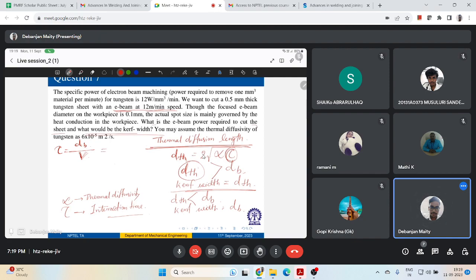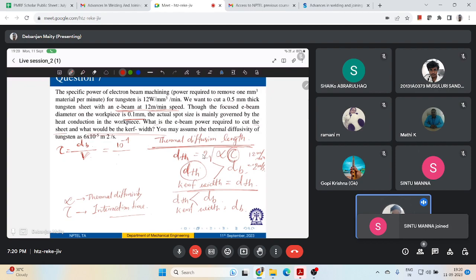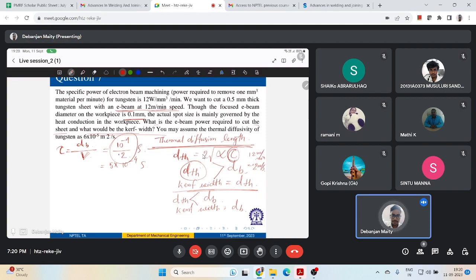So my e-beam diameter is 0.1 mm, right? So if this is 0.1 mm, that means this is 10 to the power minus 4 meter. And my V is 12 meter per minute. So 12 meter per minute is how much? 12 by 60, 0.2 meter per second. So this is my tau. How much is this coming? 10 to the power minus 4 by 0.2. This is coming as 5 into 10 to the power minus 4 second. Okay.